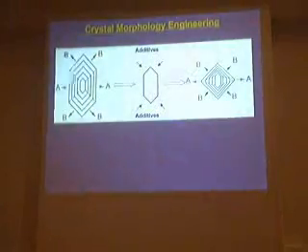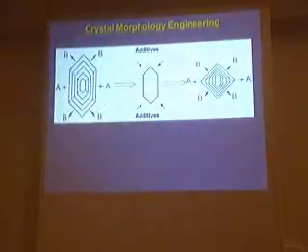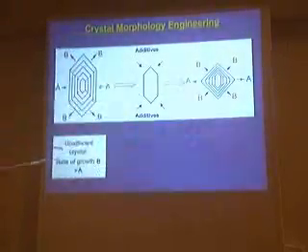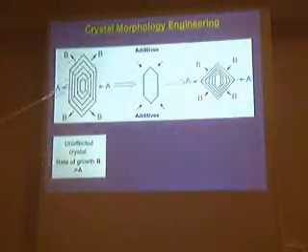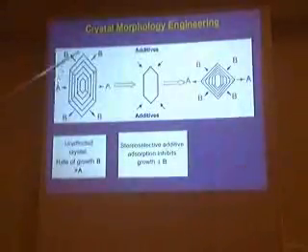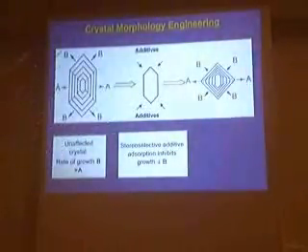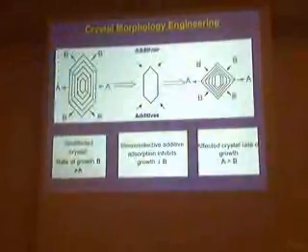So you can modify the surfaces of the various crystals that you have by adding some specific additive into the system. And from this morphology, you can in principle deduce some information about the binding of the molecules to the various faces of the crystal. Okay? This is the unaffected crystal. The rate of growth of B is very large as compared to A, therefore this phase is less expressed than this one. And then after that, you have stereoselective adsorption to some surfaces B, and then what will happen finally, the surface of the B will be much larger as compared to A.